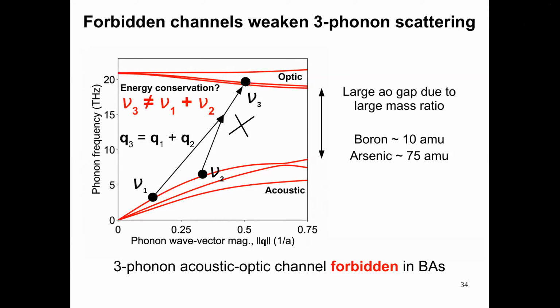So this 3 phonon acoustic optic scattering channel, which is actually one of the most dominant scattering channels in most other semiconductors, is completely forbidden in boron arsenide. So you remove one scattering channel completely from the picture, the total scattering rates go down, the denominator goes down, the thermal conductivity goes up. And that is the microscopic origin of why boron arsenide has such a high thermal conductivity, even comparable to that of diamond.